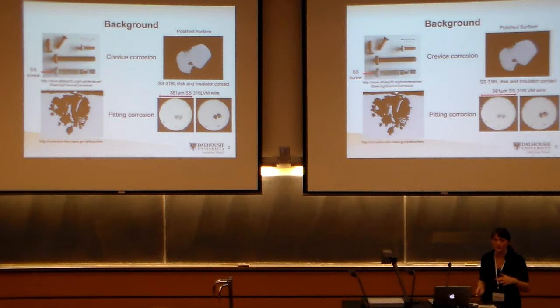Pitting corrosion is when the surface of the metal is penetrated by localized corrosion. As you can see here, this little tiny arrow shows what you would be seeing from the surface, so it doesn't appear to have affected the metal much at all. However, the cross-section shows how deep the pitting corrosion has affected the surface and how much deeper the metal is, and it can also be pretty harmful to the metals.